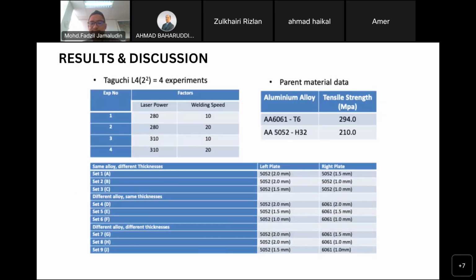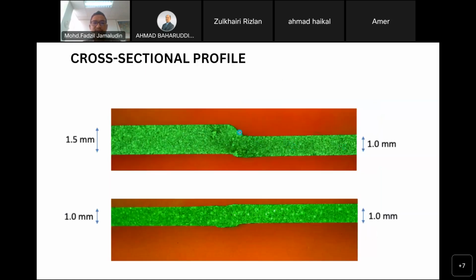So for our preliminary test, what we did was we welded 6061 and 5052, and we arranged it into a Taguchi experiment just to see what are the influencing factors. In this case, we just evaluate the laser power and the welding speed, and so on. For this test, we have tested 3 groups: the same alloy but different thicknesses, different alloys with the same thickness, and a different alloy and different thicknesses. And what we have found is the output of the cross-sectional profile.